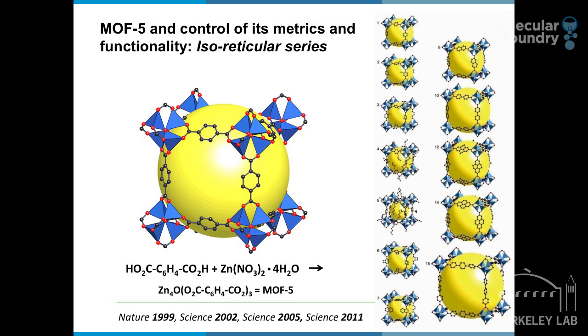However, something quite fundamental was uncovered soon thereafter, and that is that for this special structure, one can functionalize the organic units to make essentially pores with different functionalities. And also one can expand the pores so that you have increasingly larger pore openings. This was a major discovery because one can do both of those things without changing the underlying topology of the structure. And it meant we can design solid state structures, something that science has been waiting for quite some time.